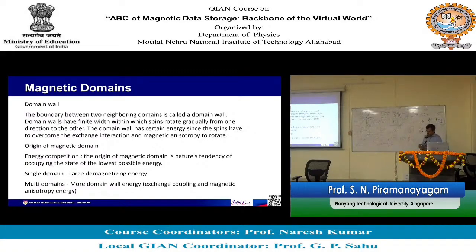Okay. So, ferromagnetic properties are maintained because the neighboring spins are parallel, but the system breaks into many regions and the magnetization of those regions points in different directions. As a result, net you will have zero magnetization. Okay. So, that brings us to this topic of magnetic domains.